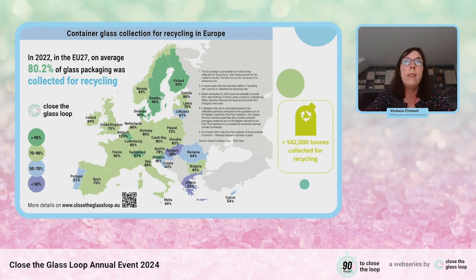So I won't go into the details, but just to give you an example, that's particularly visible for Bulgaria, for example, where the amount of packaging placed on the market increased by 12%, while the collected tonnage grew by almost 23%. So quite a huge increase. And it's worth noting that Bulgaria, but Slovakia as well, are now above the 80% collection rate.